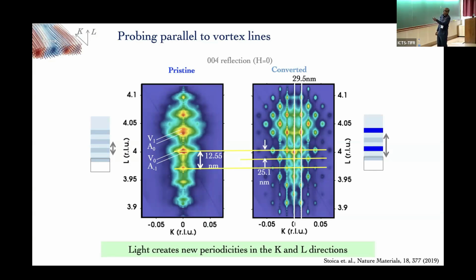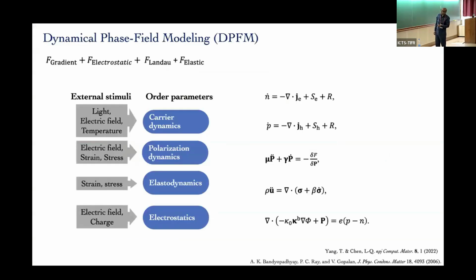And the same sort of thing happens in plane. In plane, there was no periodicity here. Suddenly there is a 30 nanometer periodicity in the plane along these spring roads that we are talking about. So, okay, what happened here? So phase field modeling was important. Phase field modeling takes free energies. It's a continuum model, with the Landau free energy, which is polarization energy, elastic energy. Electrostriction couples these two energies, and gradients take care of interfaces, gradients in polarization.